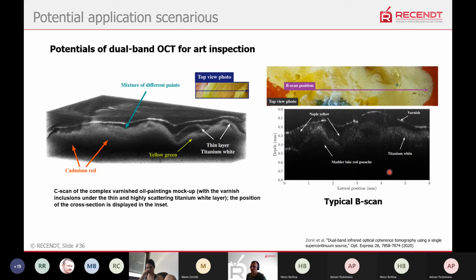Then it's of course paints. For paints, I have a feeling that OCT at 2 micron might be better because of scattering. So scattering gives us also some information, because sometimes where mid-infrared OCT just goes through and you don't see scattering, you can't differentiate different layers or different planes, and here near-infrared OCT can work better in some cases. So it's just some typical scans. So there's some oil paintings, mock-ups that I made.